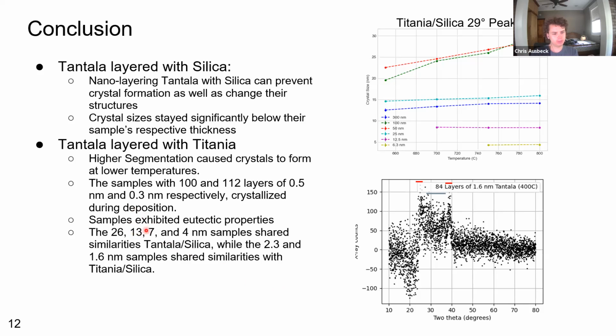We also noticed that samples exhibited mixed properties. So in this case right here, as you can see, we have our main titania peaks. And we also have these mixed peaks as well that are from mixed crystal structures that don't correspond to either titania or tantala. Also, the 26, 13, 7, and 4 nanometer samples share similarities with tantala silica, while the 2.3 and 1.6 nanometer samples share similarities with titania silica. So as we got to thinner layers, titania became a more prominent crystal structure.